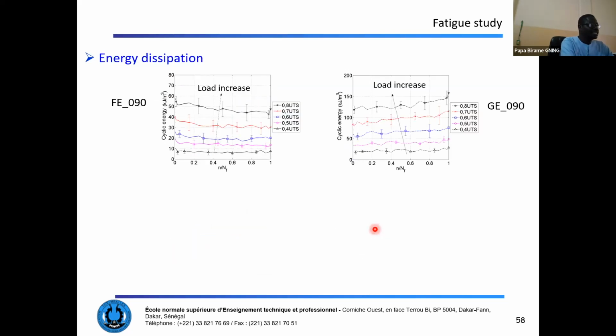So when we look at the size of the hysteresis loops, which is the energy dissipated, we can see that as much as the loading level is important, you have the importance of the energy dissipated.